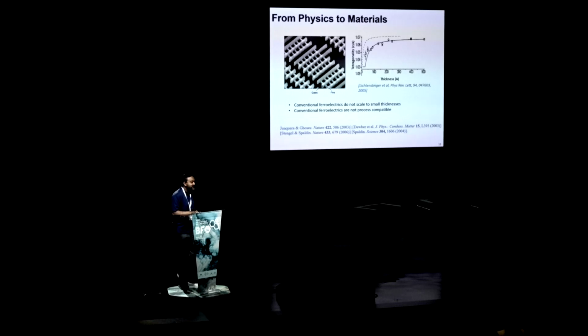That is 58 silicon atoms. And that has to contain your gate oxide, gate metal, and other things. So right now, the gate oxide in our transistors is only 1.8 nanometers thick. So I was basically told that if you lose ferroelectricity below 5 nanometers, there's no way you can use it for electronics, because the advanced devices need 1.8 nanometers. As you go farther, you will need even less.